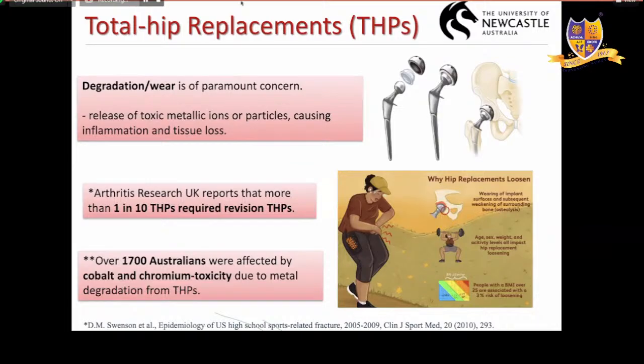One of the main reasons is wearing of implants causing debris of particles, right? And in fact, not long ago, over 1,700 Australians were affected by cobalt chromium toxicity. That's again a hip replacement implant, due to metal degradation from THPs. Okay, so we don't have an option. We have to use this material, but research is going on in improving the properties of them by biocompatible coatings and so forth. But do we need these materials for mini implants?